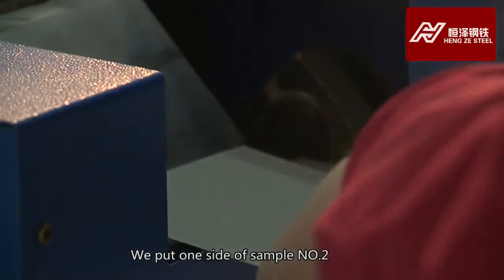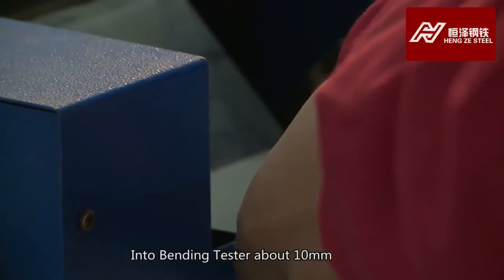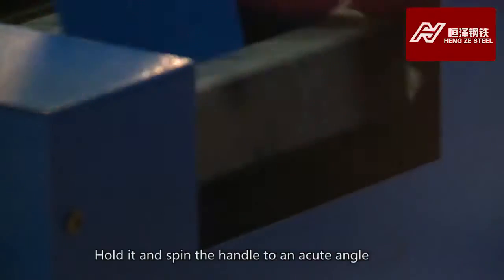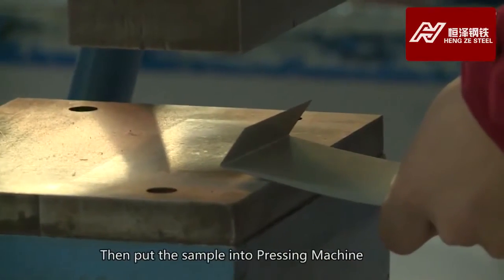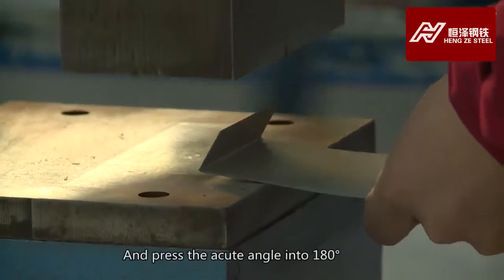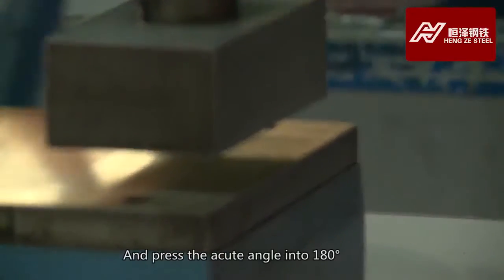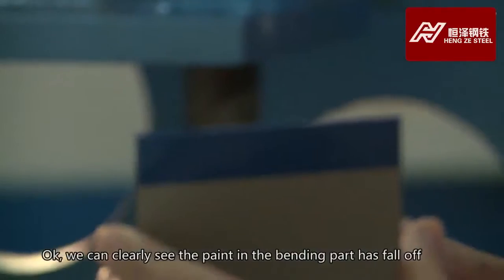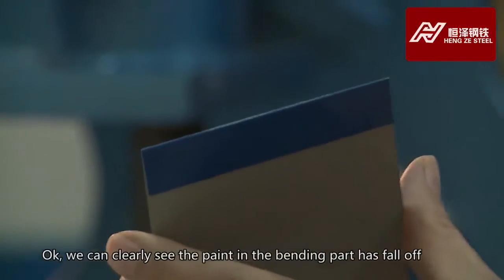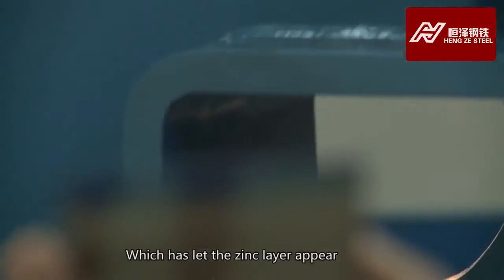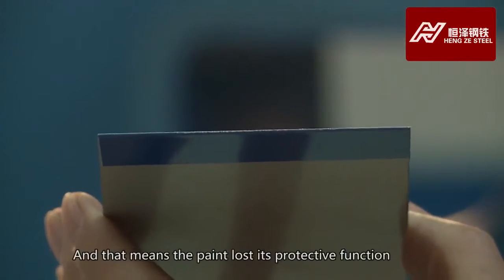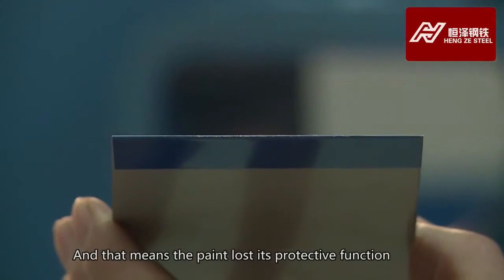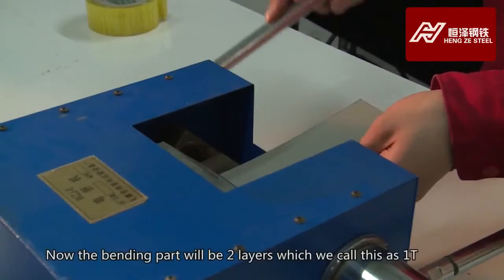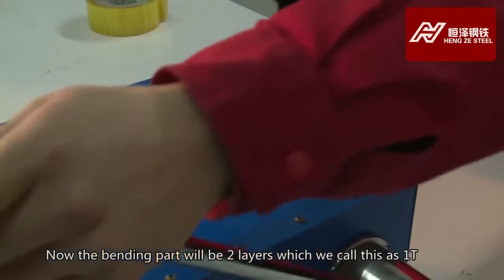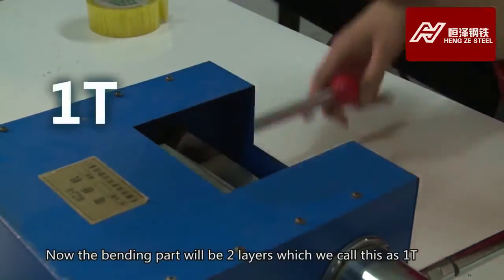We put one side of sample number 2 into the bending tester about 10 millimeters, hold it and spin the handle to an acute angle, then put the sample into the pressing machine and press the acute angle into 180 degrees. Okay, we can clearly see the paint in the bending part has fallen off, which lets the zinc layer appear. That means the paint lost its protective function. Now the bending part has 2 layers, which we call 1T.